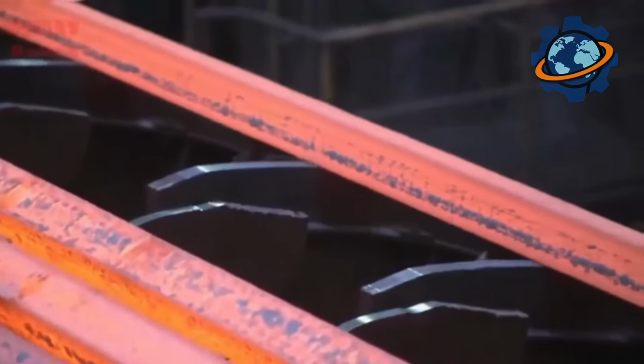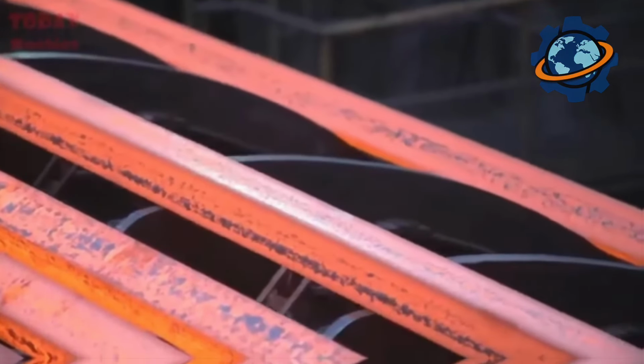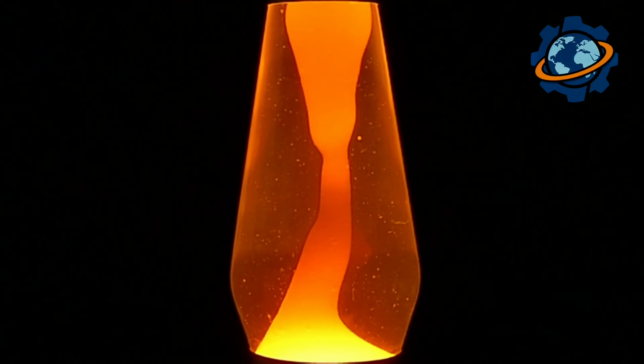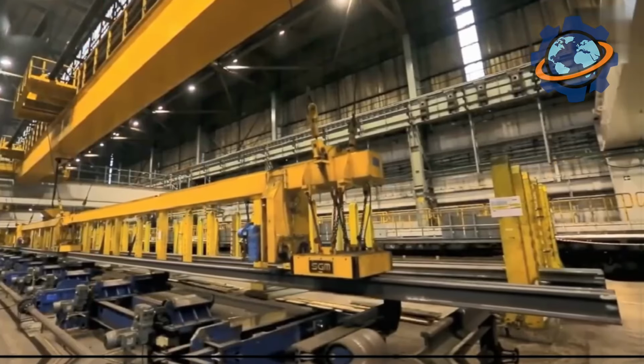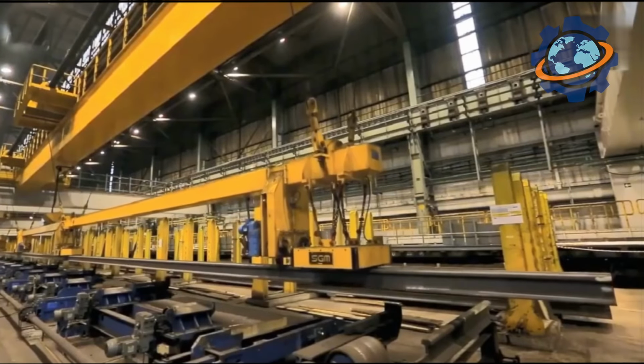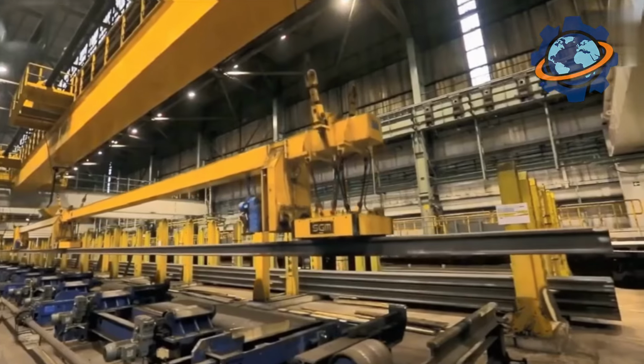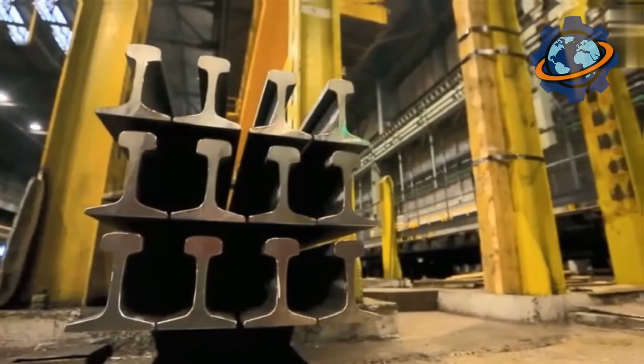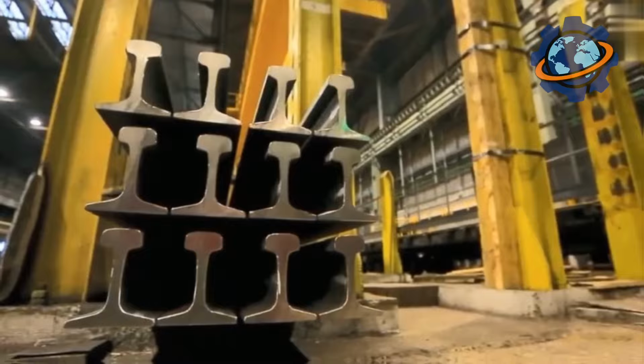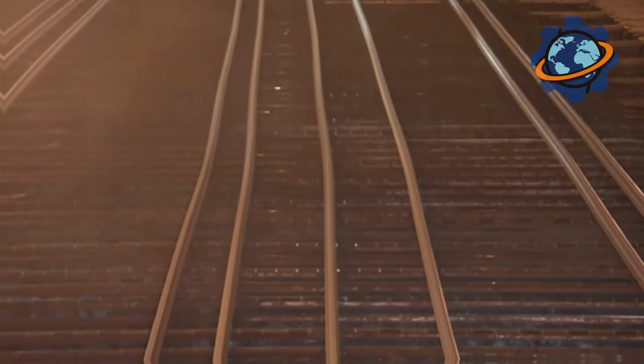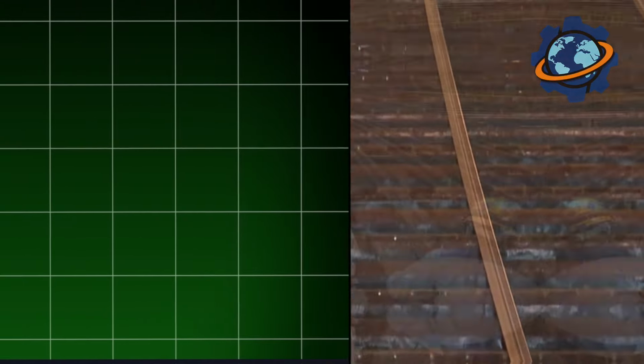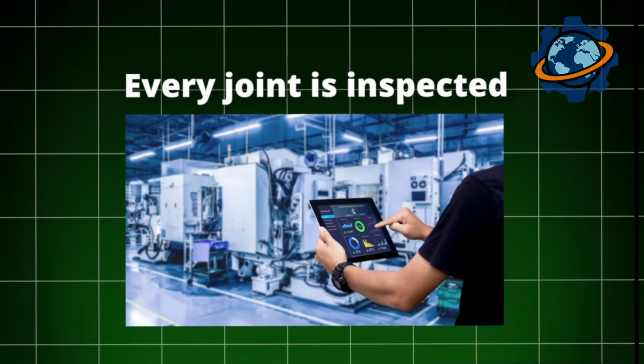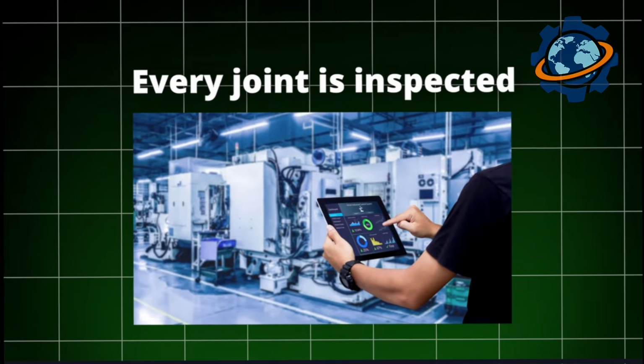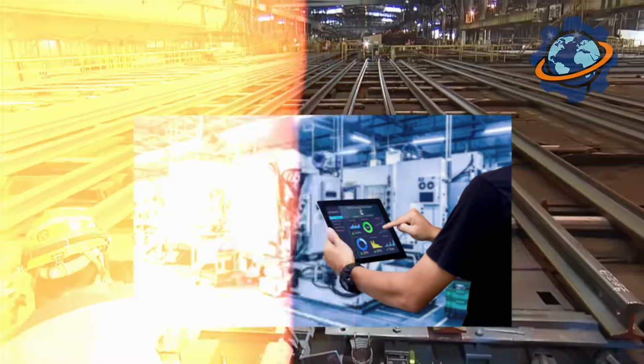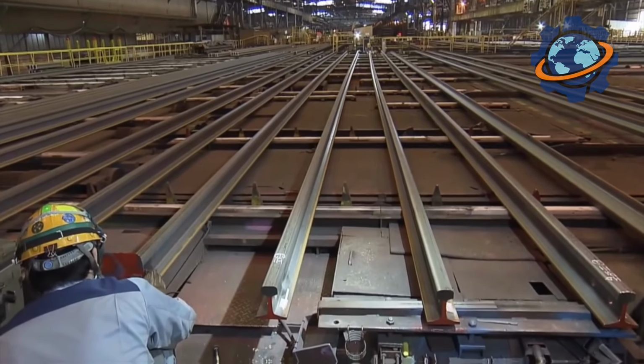The temperature hits a scorching 4,500 degrees Fahrenheit, 2,500 Celsius. This molten metal flows into both parts of the rail and fills the joint area. When it solidifies, it creates a monolithic bond, stronger than the rail itself. After that, the excess metal is trimmed off, and the weld is ground down to a perfectly smooth level, without a single bump. Every joint is inspected, with ultrasound or eddy currents, to make sure there are no hidden microcracks. These long rails are easier to transport than you'd think.